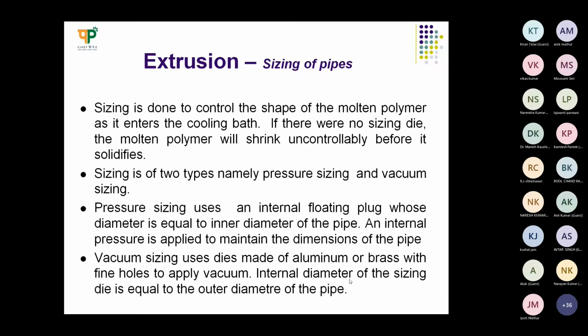Sizing is of two types, namely pressure sizing or vacuum sizing. Either you can suck the air so that it will stick onto the die, inside the sizing die, and it will maintain the shape, or you can use inside pressure also. Pressure sizing uses an internal floating plug whose diameter is equal to the inner diameter of the pipe. An internal pressure is applied to maintain the dimensions of the pipe. I will just show the process, then you can understand more.